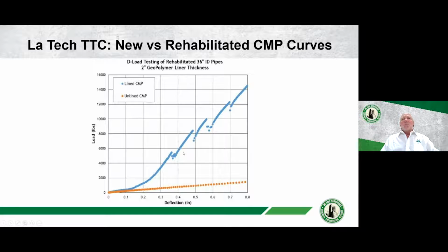It increases up. You can see here, this is actually the location of first cracking, which is likely in the crown. And so what we want to do in our design methodology is make sure that we stay at a load that is below this first cracking. And in the real situation, if you take a look at it in the field, most of the loadings that we're going to get in the field are somewhere down in this 1,000-pound range. So in this lower section of this curve, we have a lot of safety factor in this design. But it is very, very calculable, and that's one of the things I liked about it.